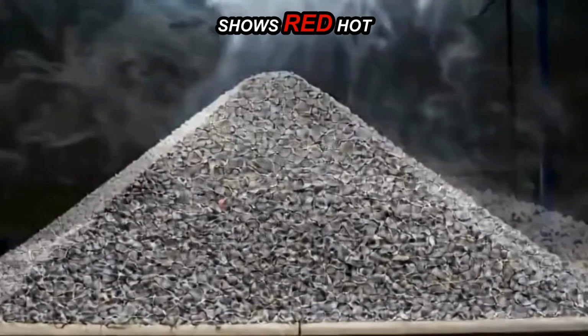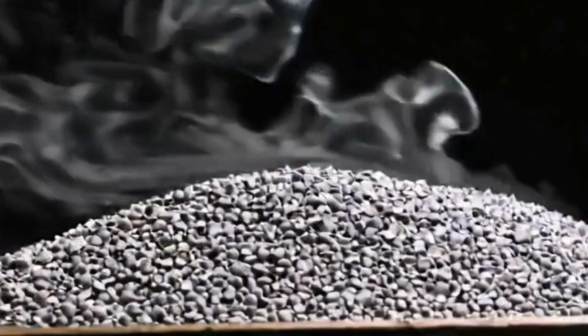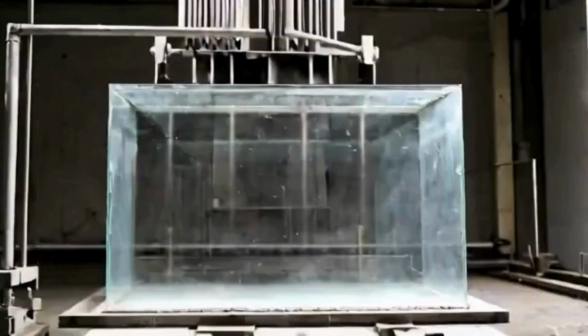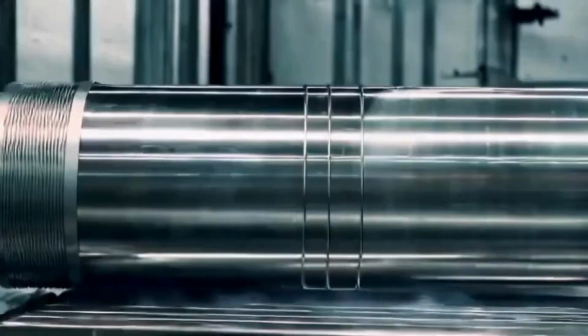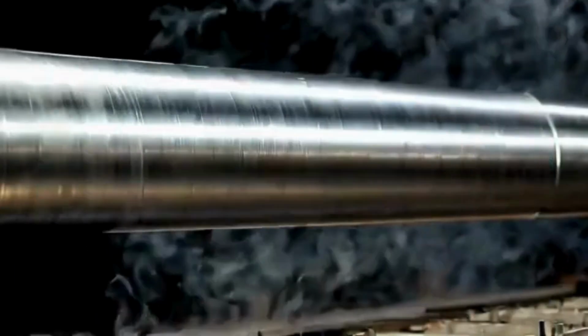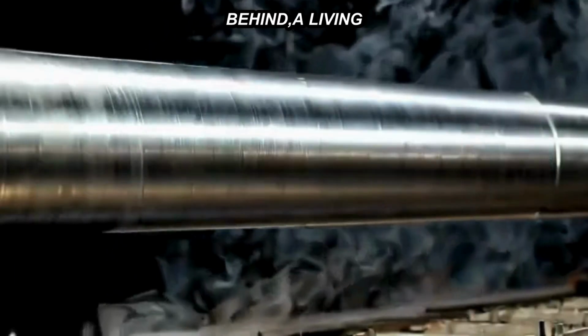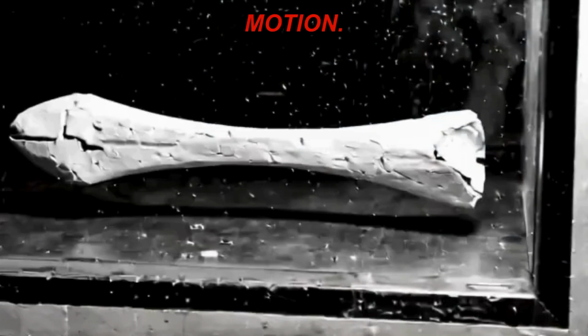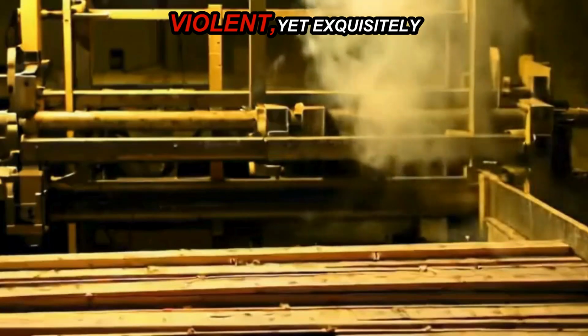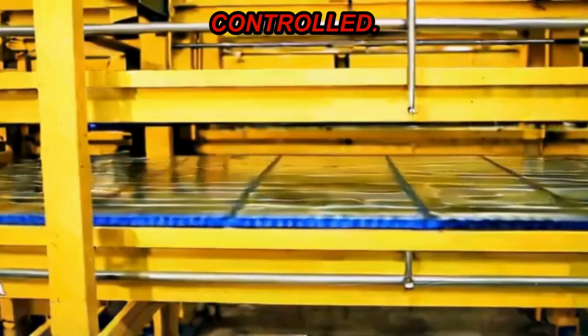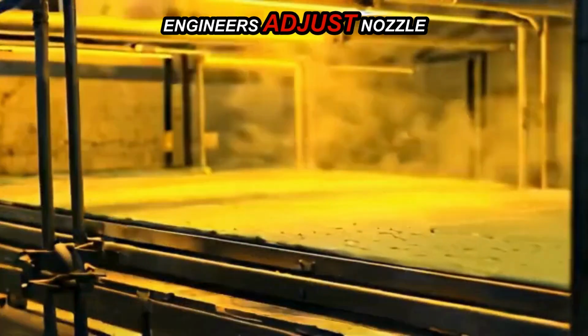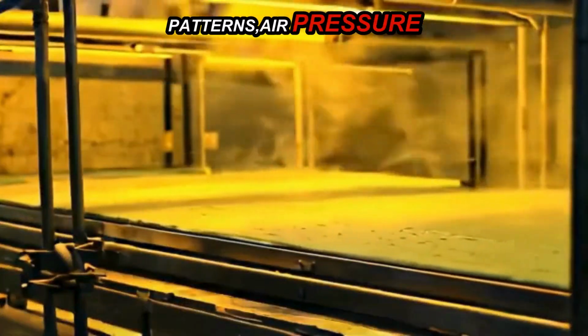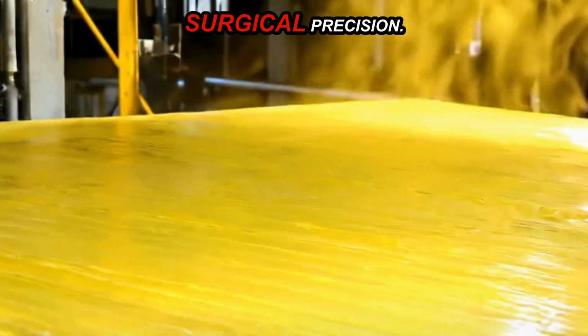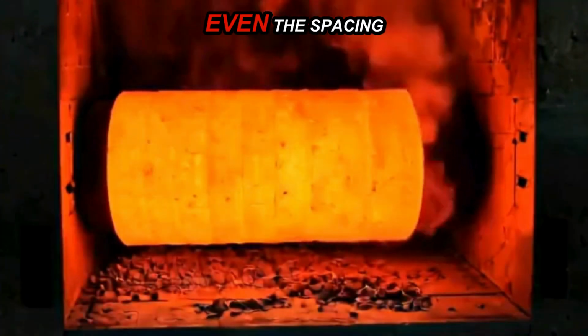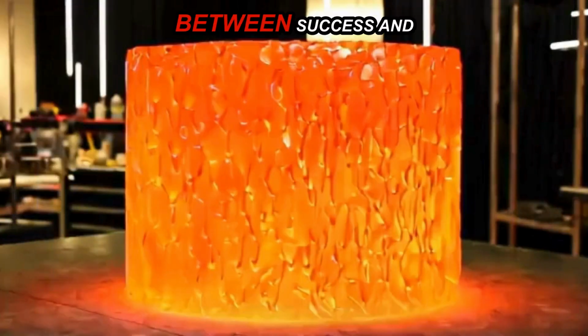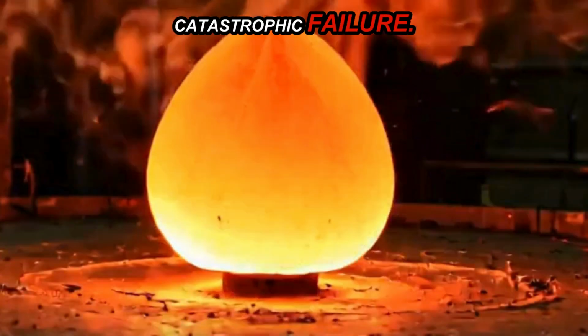Slow-motion footage shows red-hot glass meeting the cold blast. In a fraction of a second, crystals freeze across the surface, like ice forming on a winter pond. The interior lags behind, a living core still in motion. The process is violent, yet exquisitely controlled. Engineers adjust nozzle patterns, air pressure, and timing with surgical precision. Even the spacing of nozzles can make the difference between success and catastrophic failure.